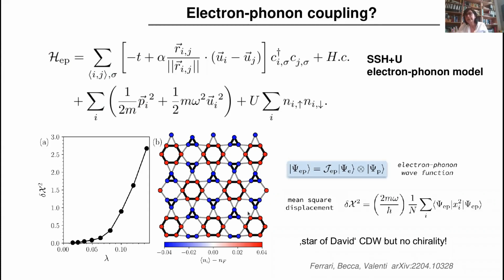From the theoretical point of view, it's rather clear that the electron-phonon coupling is most probably the interaction driving the system into this charge density wave. The question is, if there is chirality, if these charge density waves are in fact chiral, where does this chirality come from?